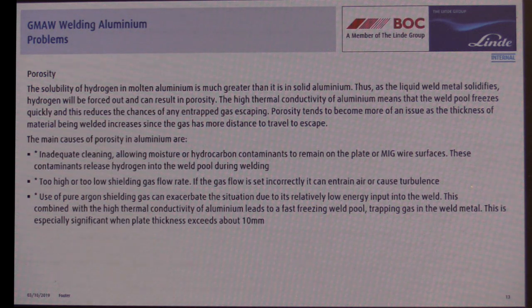Use of pure argon shielding gas can exacerbate the situation due to its relatively low energy input into the weld, so it hasn't got the same heat properties as a helium-based gas. Combined with the high thermal conductivity of aluminium, this leads to a fast freezing weld pool, entrapping the gas again. This is especially significant in materials above 10 millimetres.